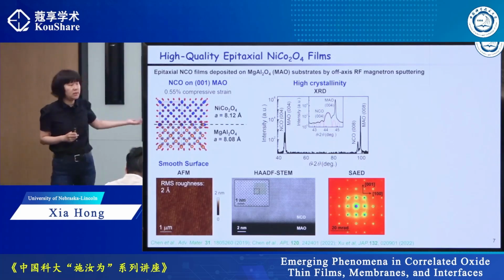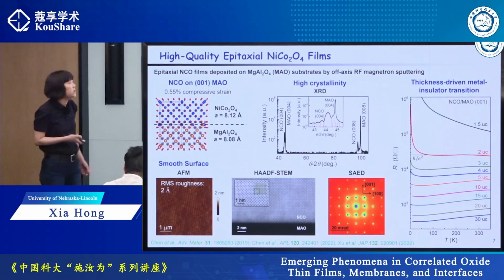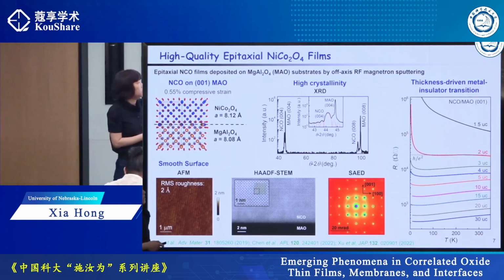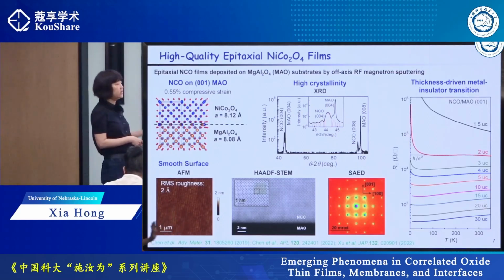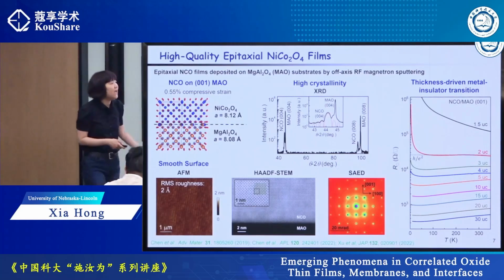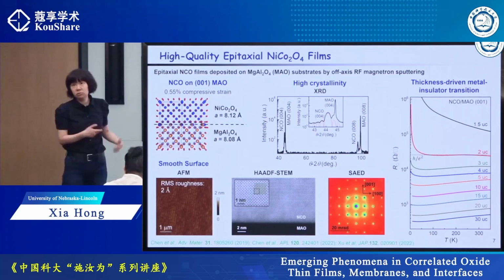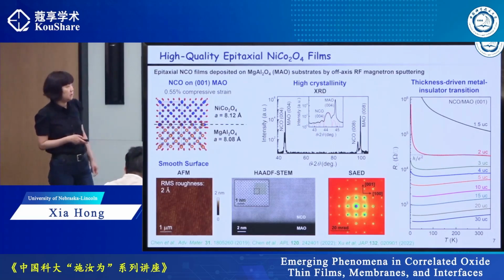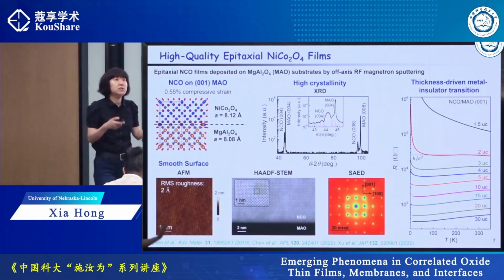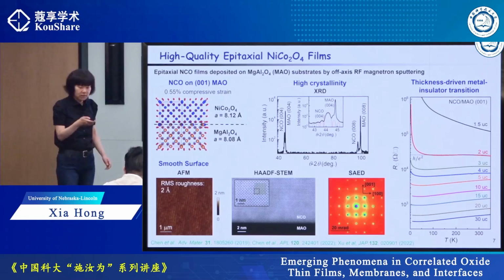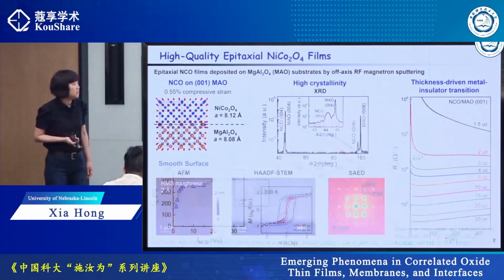You can see it has a smooth surface, high crystallinity. What's shown here is the sheet resistance as a function of temperature for films of different thickness. And you can see we can maintain metallic phase down to 3 unit cells. That's 2.4 nanometers. And the sample only becomes insulating when it's reduced to 1 unit cell, when the sheet resistance reaches the quantum limit of h/e squared. So it suggests there's a dimensionality that induces this metal-insulator transition.